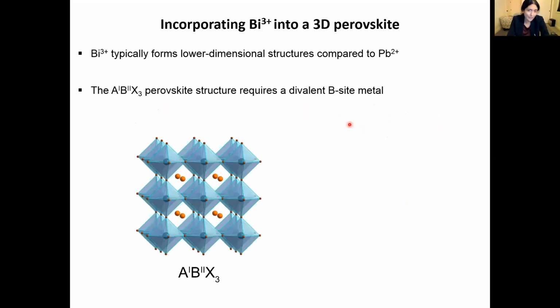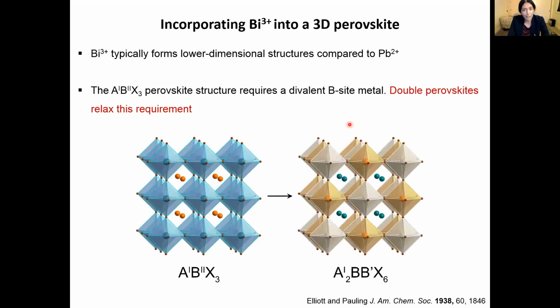And we found that we could do this quite simply by working with another subfamily of perovskites known as double perovskites. So these materials have also been known since the 1800s, but we were amongst the first to evaluate double perovskites as solar absorbers. So in a double perovskite, instead of a single metal, we have two octahedral metals, B and B prime. They alternate in all three dimensions. And in a single perovskite, this octahedral metal site has to be 2+. In a double perovskite, the average has to be 2+, but we can distribute that charge unequally as 1+ and 3+, or 2+ and 2+, or nothing and 4+. It still averages out to 2+.